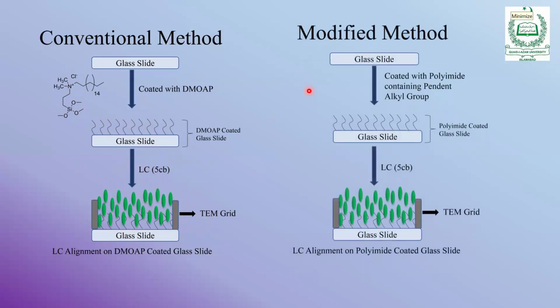What we have attempted is we replaced this DMOAP with a polyimide which contains pendent alkyl groups. So we are actually doing the same thing, but the difference is that we are using a polyimide, a plastic, on the glass slide. The DMOAP is a simple coating. It can wear off from the glass slide. But this polyimide-coated glass slide is resistant as compared to this one, so we can reuse it. The other thing is the same, we use the liquid crystal. We put the TEM grid and then we apply the analyte solution.